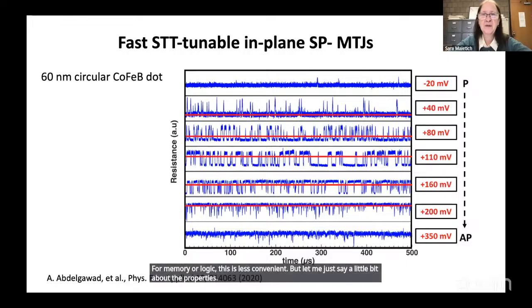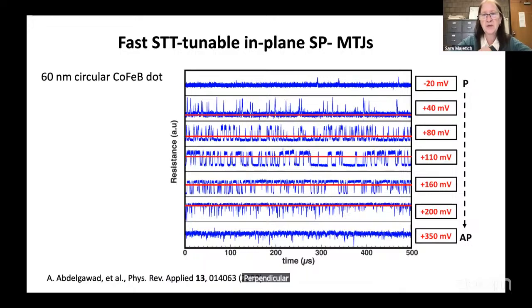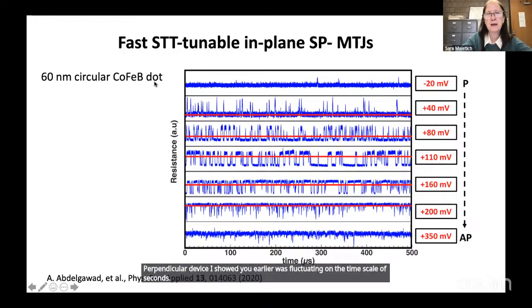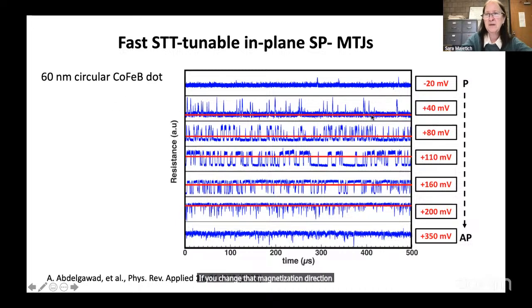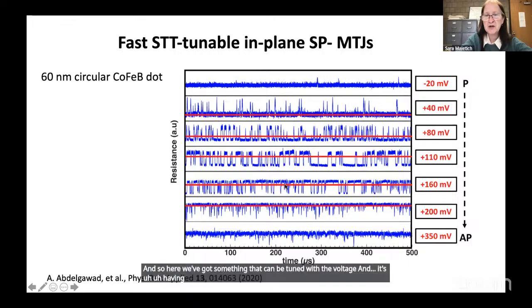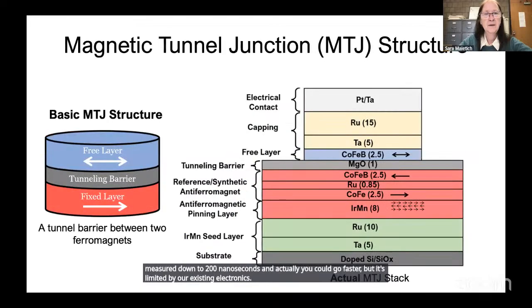But let me just say a little bit about the properties. Again, you want your devices to be faster. The field tunable perpendicular device I showed you earlier was fluctuating on the time scale of seconds. If you change that magnetization direction to in plane, you speed it up. And so here we've got something that can be tuned with the voltage, and it's having fluctuations here we're showing on the microsecond scale. We've measured down to 200 nanoseconds, and actually you could go faster, but it's limited by our existing electronics.